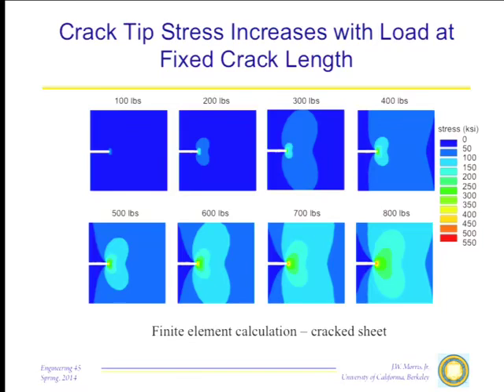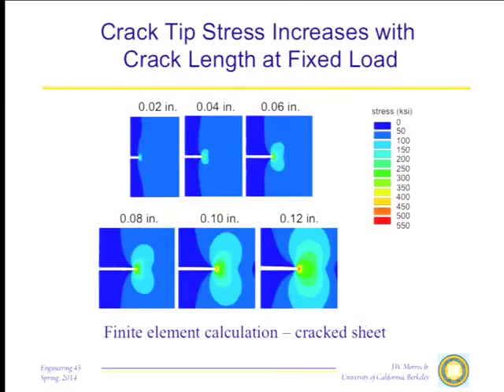And you see, in this case, you fix the length of the crack and increase the applied stress or the load. And as you do that, you see the stress field getting bigger and bigger and bigger, and the stress here at the crack tip getting more and more and more intense. And the stress here at the crack tip, even under fairly small loads, is some 5 times the nominal stress out of the material. So it's very easy to get large stresses at a crack tip just by using the geometry of the crack. Well, the crack length is also an issue.